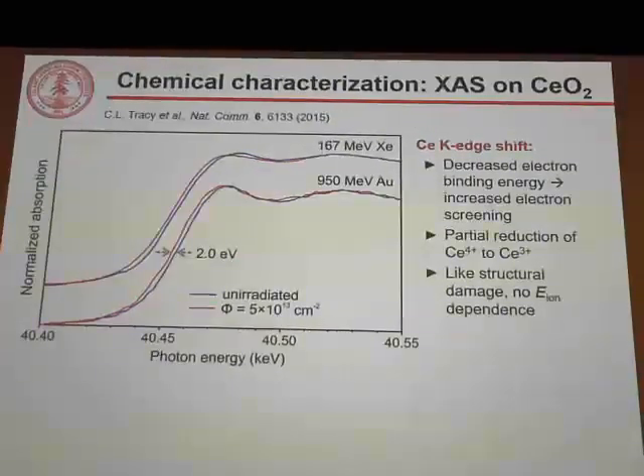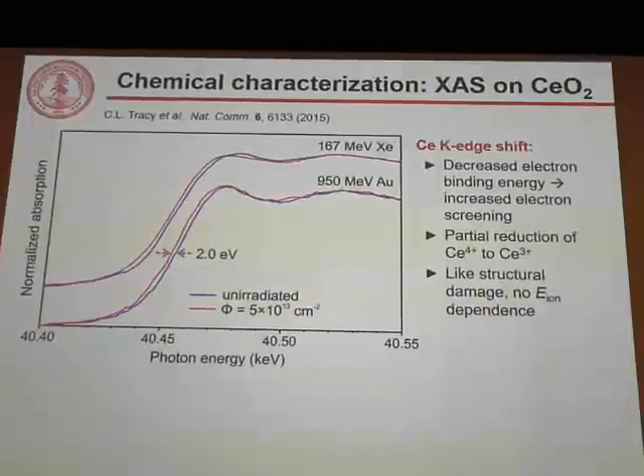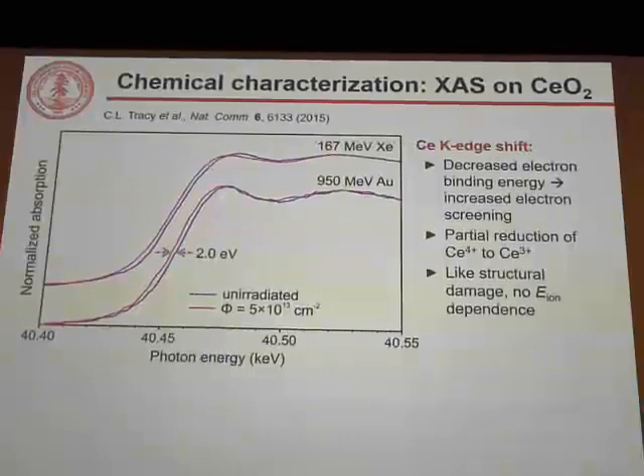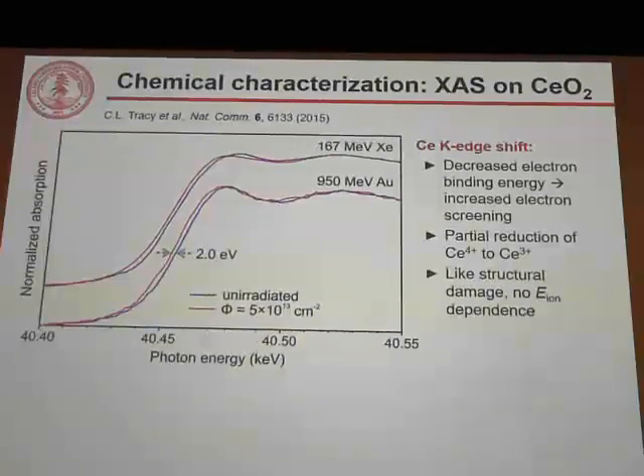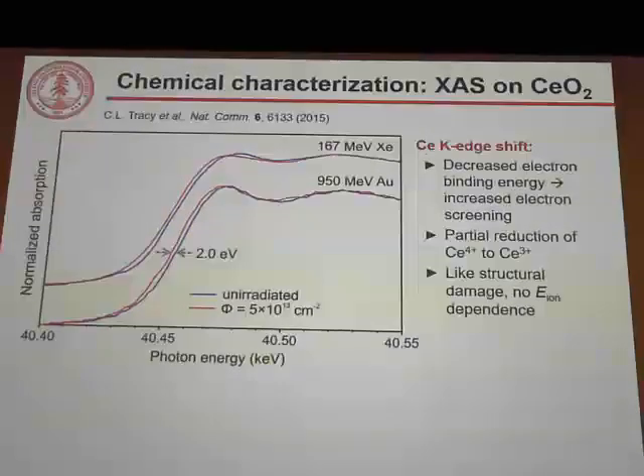The next thing we did is characterize the chemical changes that we know to occur using X-ray absorption spectroscopy. So I show here that measurement for both ion energies, and in both we observe a shift of the cerium K edge to lower energies following irradiation. That decreased electron binding energy is indicative of increased electron screening that accompanies the reduction of tetravalent cerium to trivalent cerium. So from these measurements, we know that on some cerium cations, additional electrons that have been excited are relaxing.